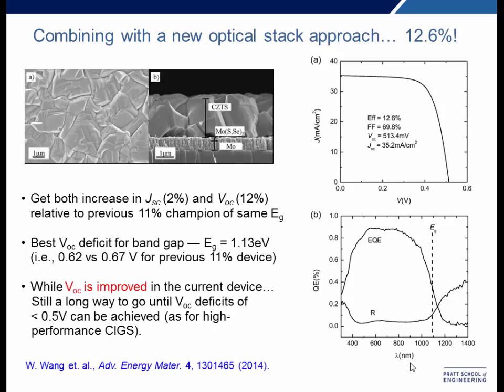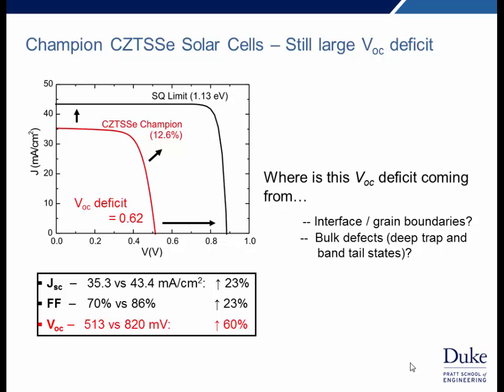And combining this with improved light management techniques, such as mentioned in the previous talk, we were able to boost both short circuit current and VOC to yield what is currently the world record for this material, 12.6% devices. And this also gave our best open circuit voltage deficits of 0.62 volts versus the previous 0.67 volts for the 11% device. And so this, again, is nice improvement in the open circuit voltage. Still not good enough. We're still pretty far from where we need to be for the Shockley-Queisser limit. And the question is, where is this coming from?